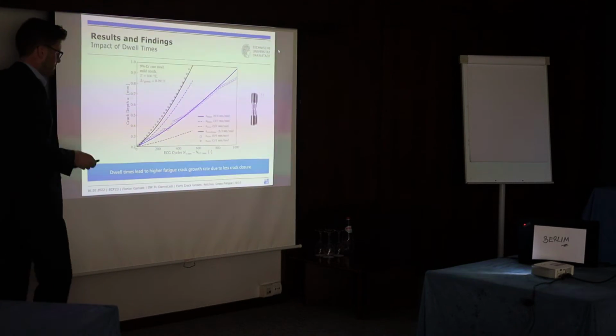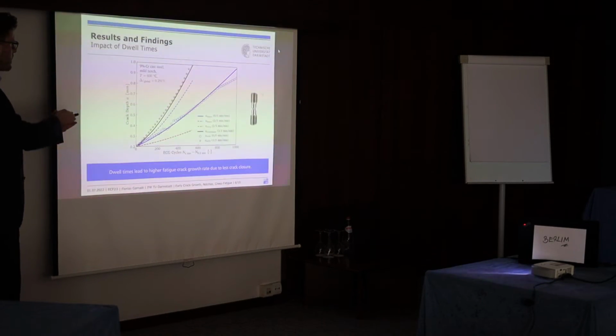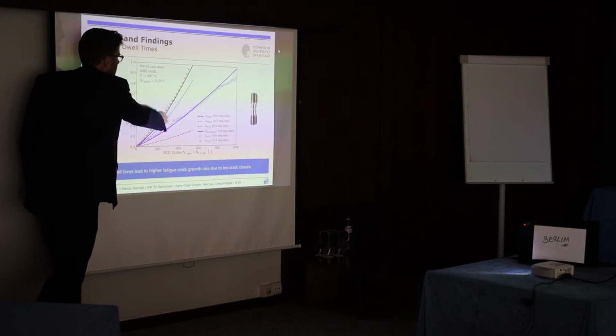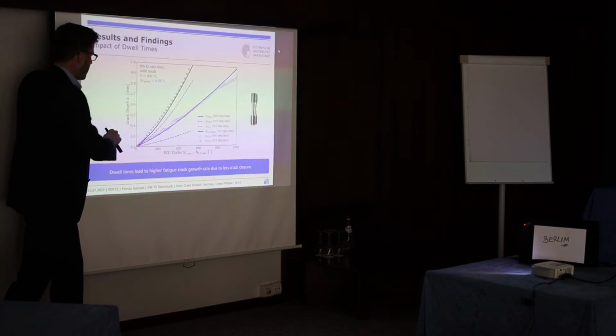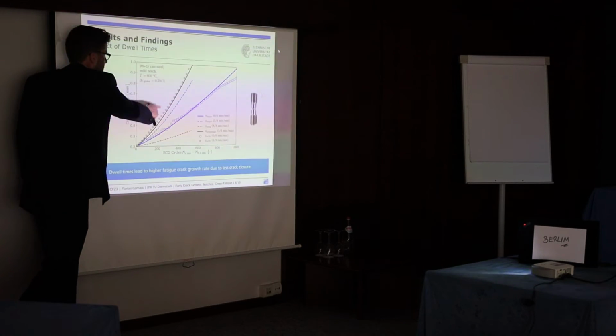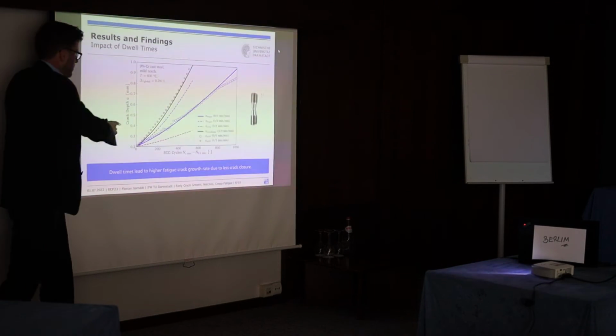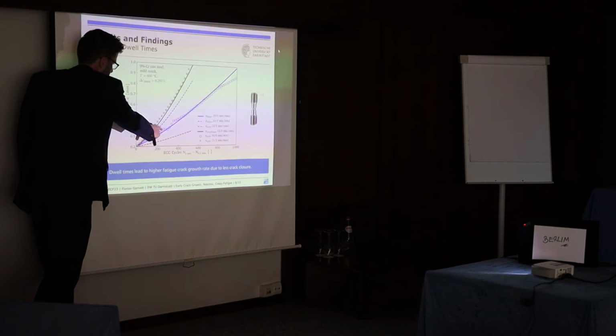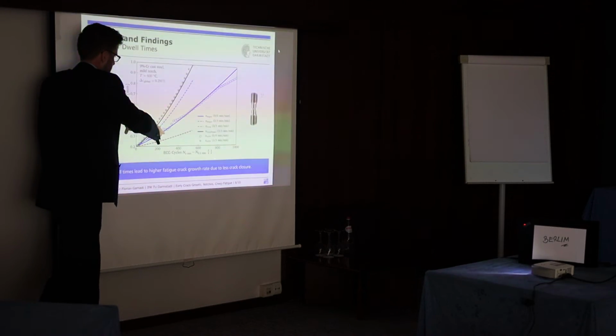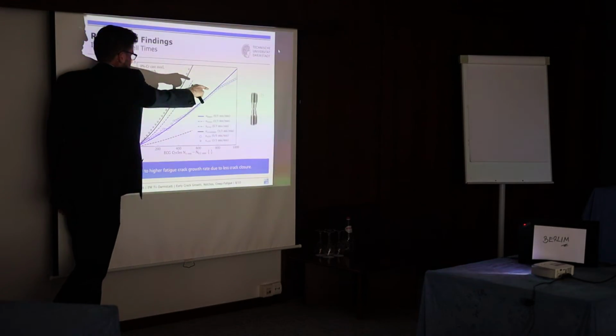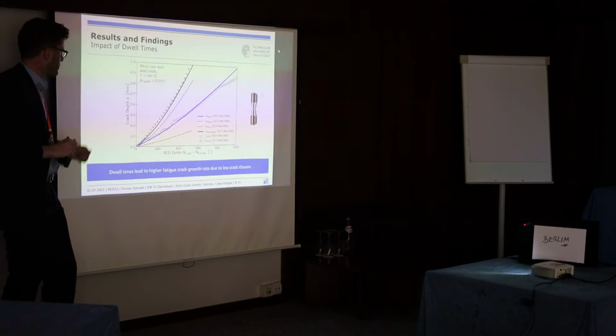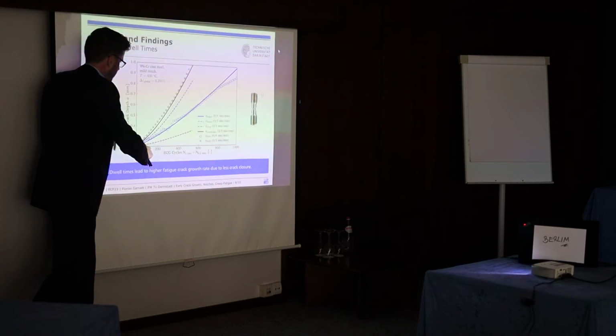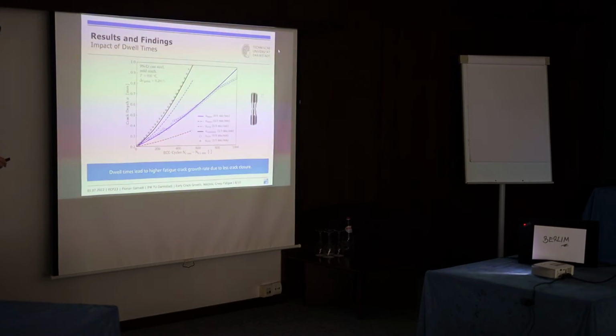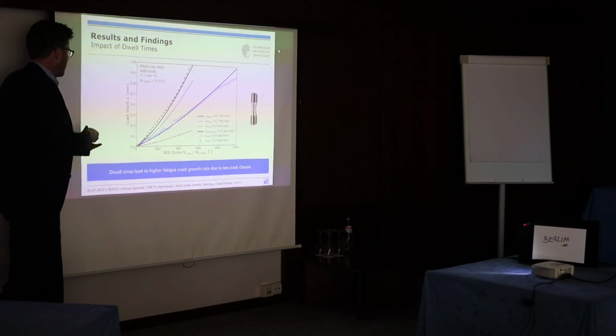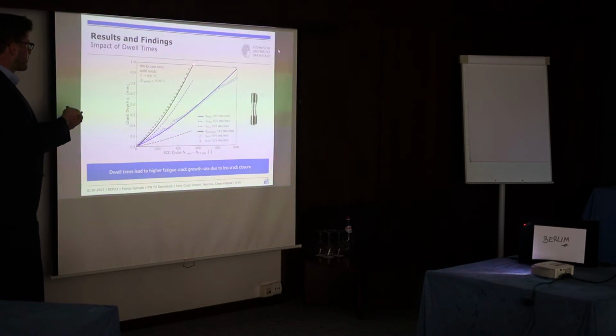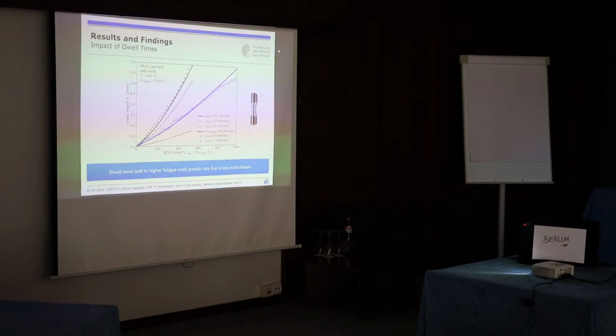You see the crack depth over the cycle number. These blue line and these blue markers belong to a pure fatigue cycle, so this is no big thing. But the black line here and the black stars, they belong to a creep fatigue loading. And this is just possible because we consider the effect of the dwell times on crack closure. And if we do so, we end up with a higher fatigue crack growth rate during our creep fatigue loading. You see the difference here. And of course, there is an additional creep crack growth occurring. So in the end, the sum gives us here a very good description of crack growth on the creep fatigue loading. This is just one example.